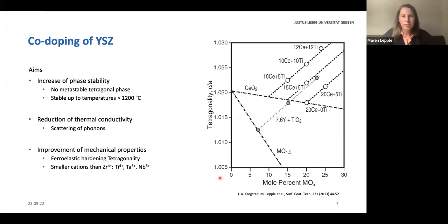So when co-doping yttria stabilized zirconia, the aim is, of course, to increase the phase stability, to make the metastable T prime phase, which is a tetragonal phase with a high tetragonality, stable up to temperatures above 1200 degrees centigrade. Furthermore, by adding additional elements, the thermal conductivity can be reduced because there's more scattering of the phonons.